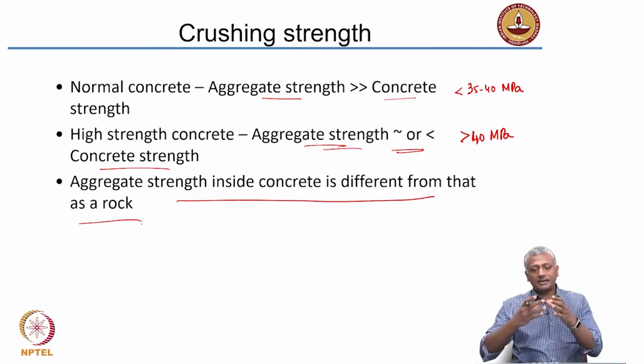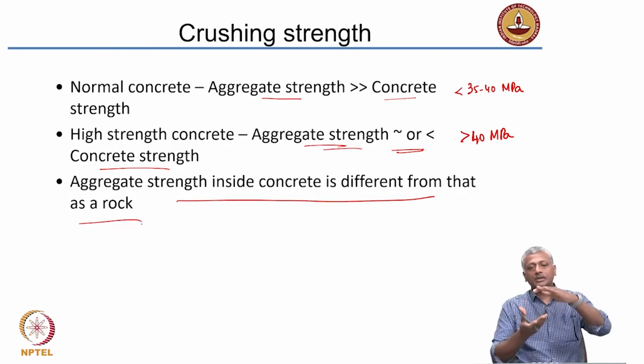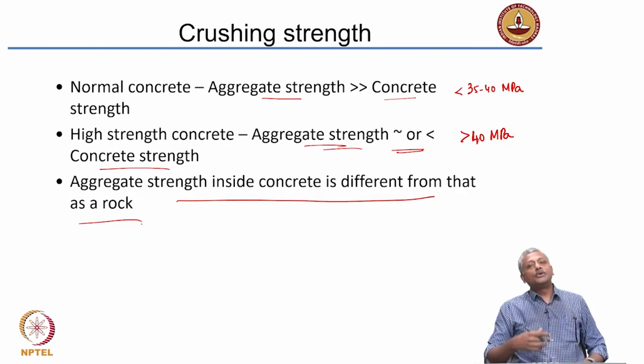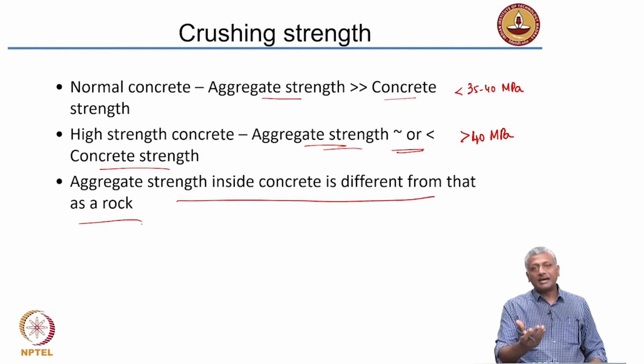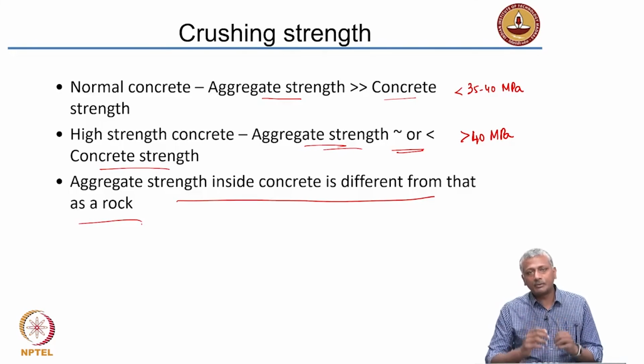So, if you take the aggregate as a cube, let us say you take a cube of granite and test it, you will get much higher strength than 150 megapascals, because granite has that strength. But when you have aggregates of granite inside the concrete, even for strengths as low as 60 megapascals, you will start seeing failure of the aggregate. That is because you have a lot of defective pieces inside. In a cube, you have a nice solid rock, but when you break it down into aggregate, its weakness or its failure planes get exposed. As a result, you will have a lower strength.